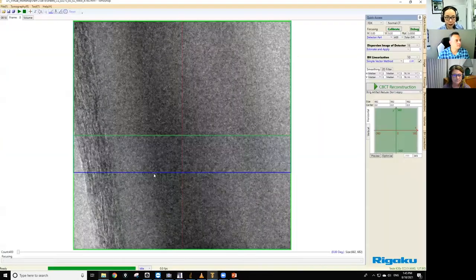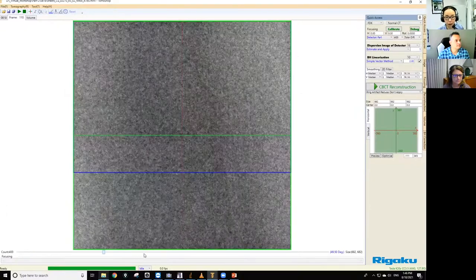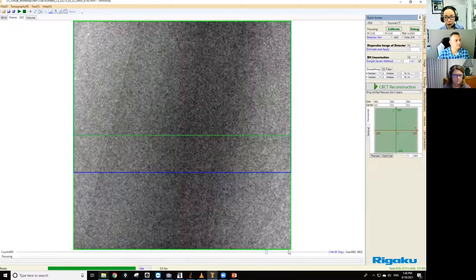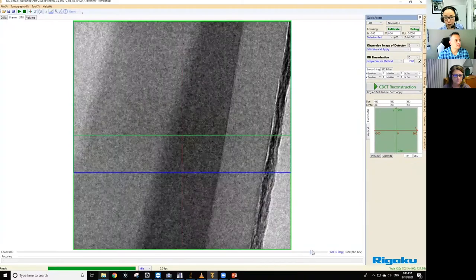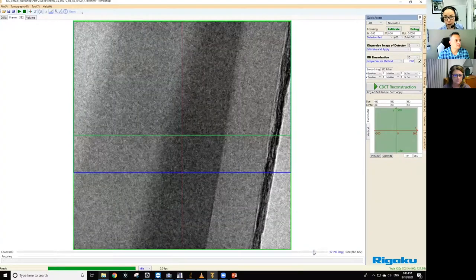So we'll look at this one. Again, we did a 3x3 binning and it got 400 projections. When you look at the sample from the side, you see the center part is darker, that's UV resin, and you have parafilm on this side, paper, and another polymer sheet on this side. And you can clearly see that the UV resin is higher density.